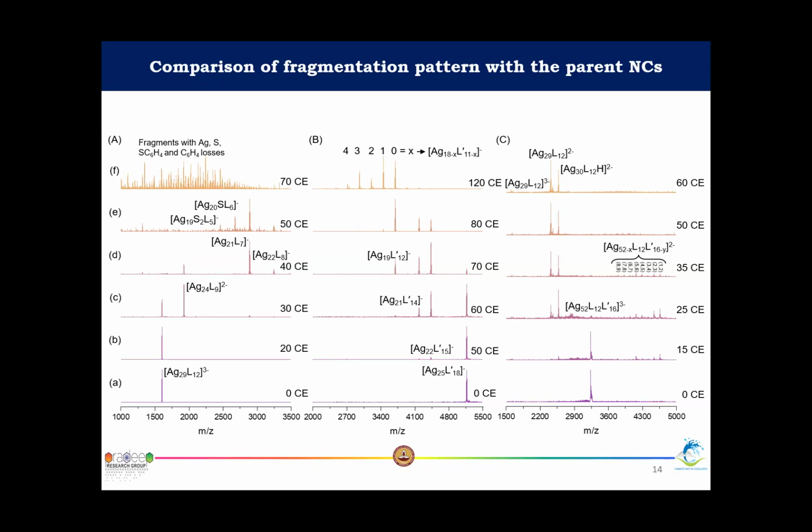So it is not thermally activated to the same extent. It is like a billiard ball hitting an elephant versus hitting an ant. I'm just comparing these two to say that you are not really transferring enough energy. That is essentially what is reflected here. It is not necessarily that you are having increased stability. This will be questioned later on by people if you were to argue like that. Okay, I just wanted to leave that. Danaka, please continue. Thank you.